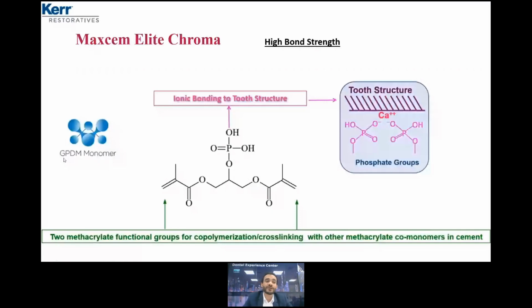As you can see here, GPDM has three heads, like a triple arm. You have a phosphate and also two methacrylates. We have ionic bonding to the calcium in the tooth structure, and the two methacrylates are responsible for cross-linking with the other methacrylates in the cement. So I can say that we have two types of bonding to the tooth structure. But what about the restoration? We also need a high bond strength to the restoration.